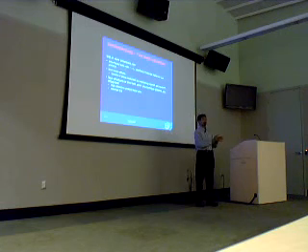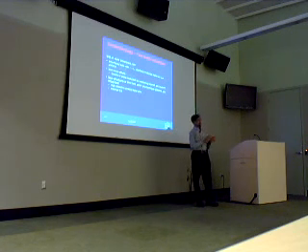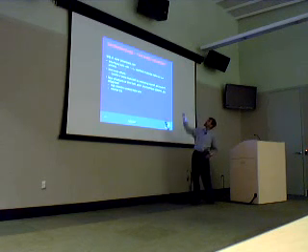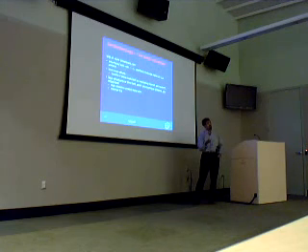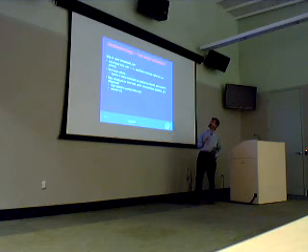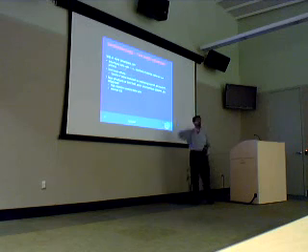People would argue intuitively that if I reduce the dimensions, I have fewer atoms. I should be able to simulate them in first principles. So why can't I do that? But it does have these two paradoxes. The size is in nano dimensions, but the interfaces to bulk ratio is much higher than 1. So this means that interfaces modulate all the behavior that we see, not bulk materials.